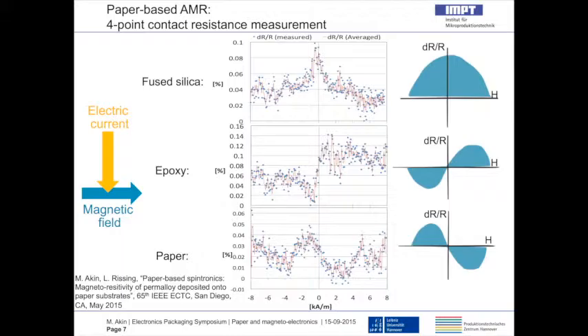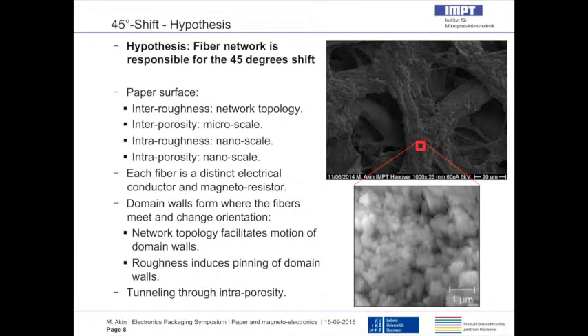Now, for the second configuration, where the electric current is perpendicular to the magnetic field, we measured a decrease in electrical resistance on the reference sample. On the paper sample and the epoxy-based sample, which is the replication of the surface of the paper, we obtained a plus minus 45-degree angle response. Then we asked ourselves, why is this happening? This is happening on the epoxy and on the paper, which only have the surface texture in common. The hypothesis we put forward is that the fiber network is responsible for that 45-degree shift. Basically, we have a shift between the two configurations we measured of plus minus 45 degrees.